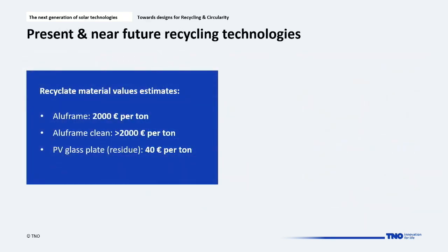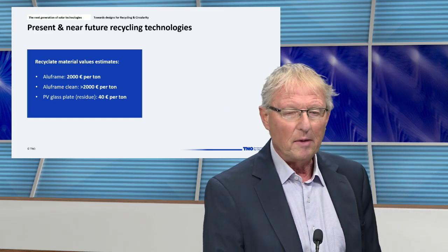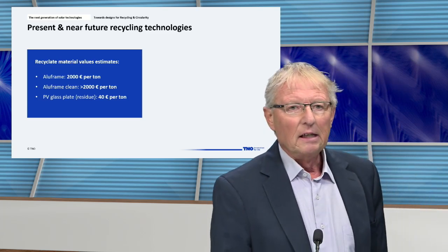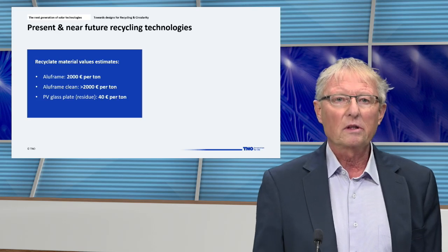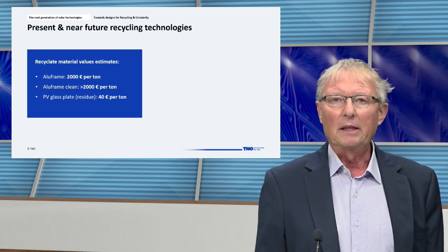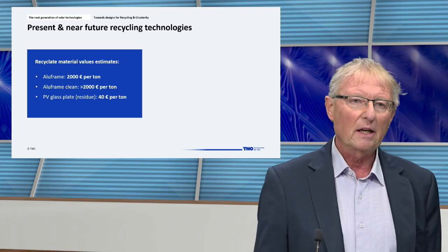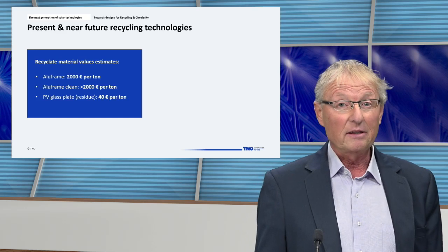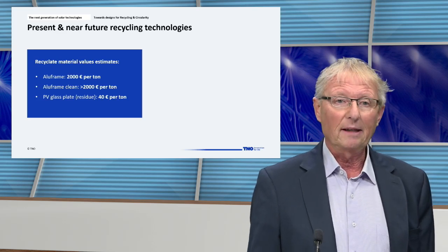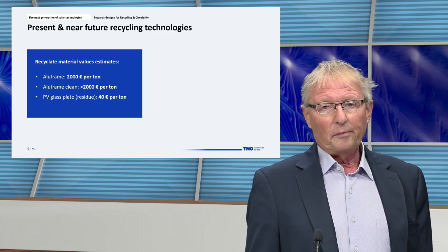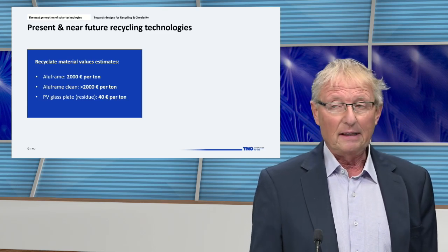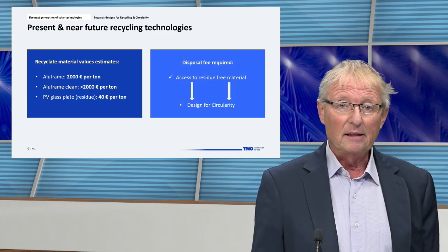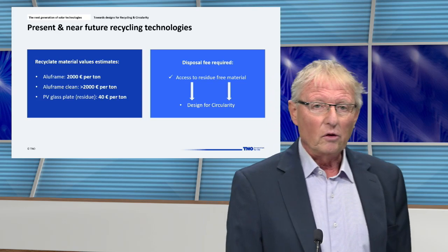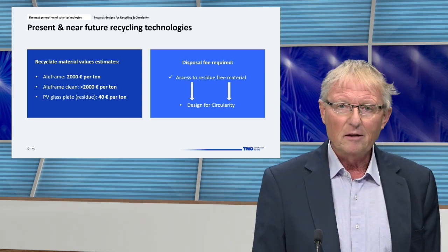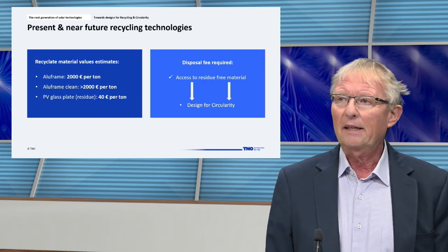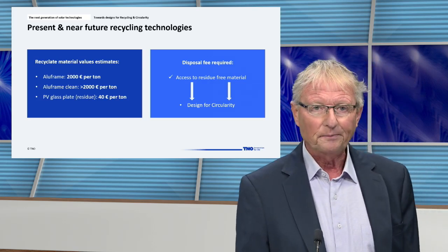So if we take a further look at the profits which can be made, and then I'm looking at dismantling again, the aluminum frame delivers us most of the money. The PV glass plate a bit less, because there is still encapsulant residue on it, and it's recasted into window glass rather than turned back into PV glass. So finally, the costs of the recycling are higher than the profits, and this requires a disposal fee. So the wish case is to have access to residue-free materials, and that brings me to the next step, and that is design for circularity.